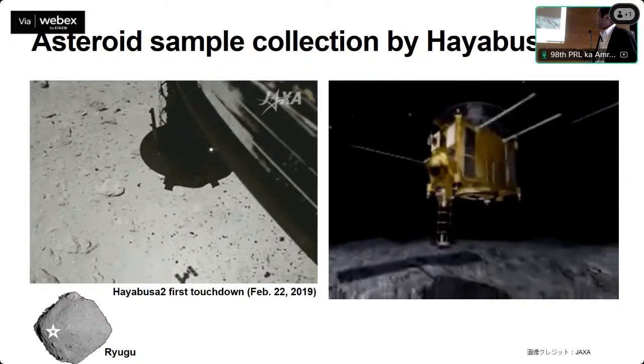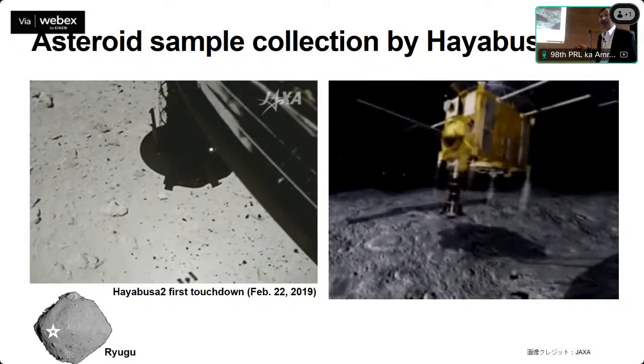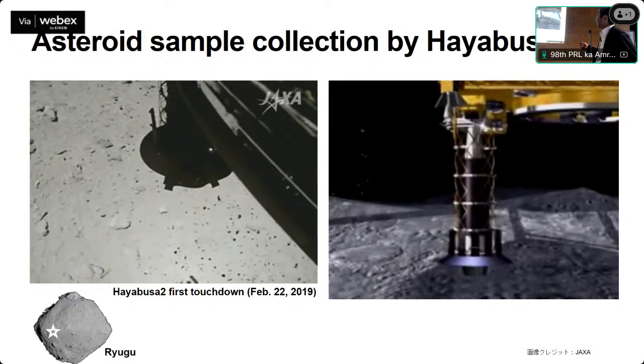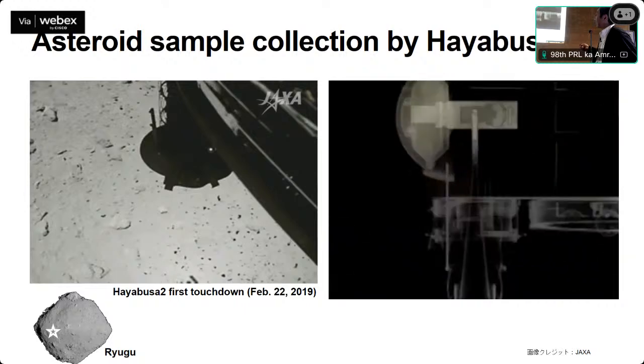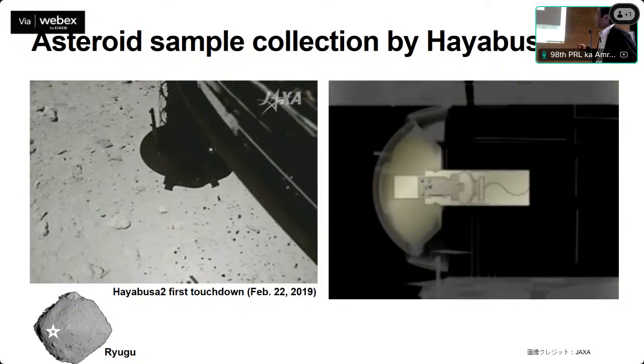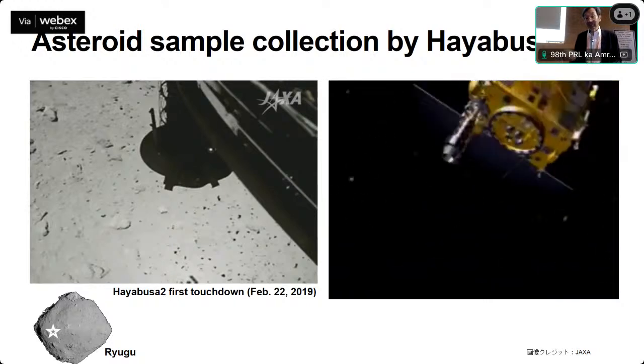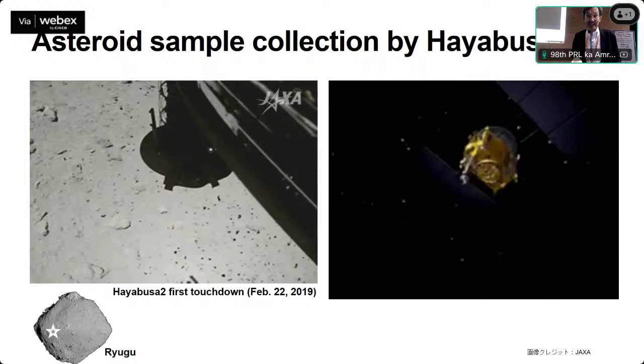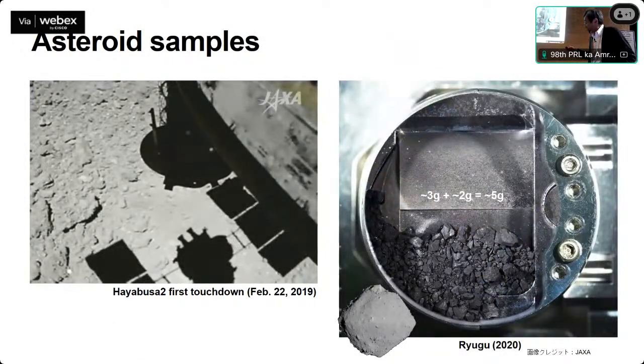And the next slide is how to sample it. The touchdown timing is about 1 second. At 1 second, the bullet impacts the surface, and the fragments go to the sample capsule, and then the sample is stored in the return capsule. So this process occurs automatically. Then we found 3 grams of the sample. When we opened the capsule in the laboratory, we found 3 grams of the Ryugu sample in the sampling capsule. And in another room, we found 2 grams. So in total, we recovered 5 grams of samples from asteroid Ryugu.